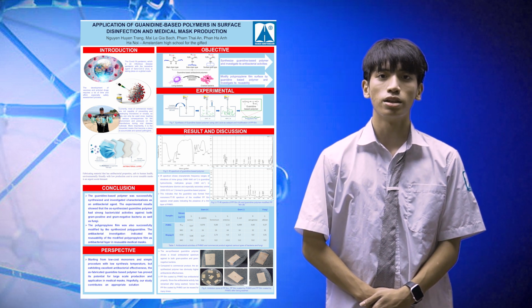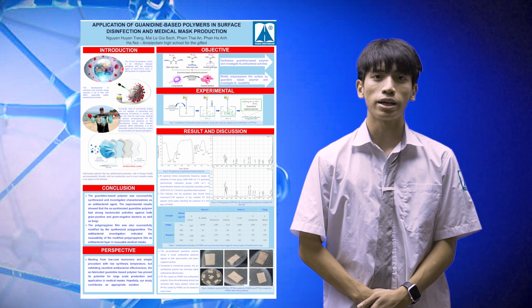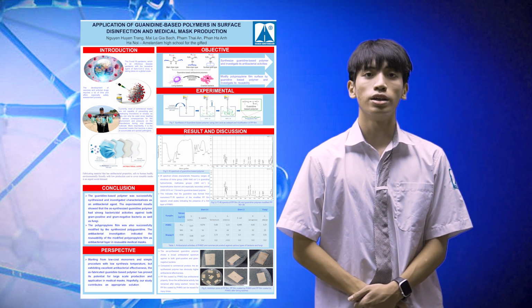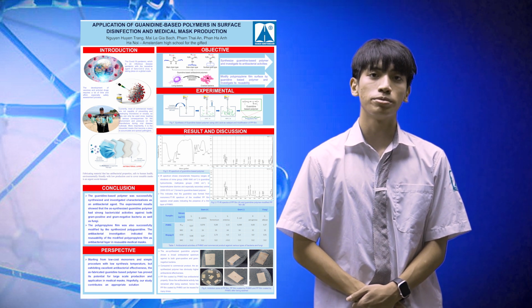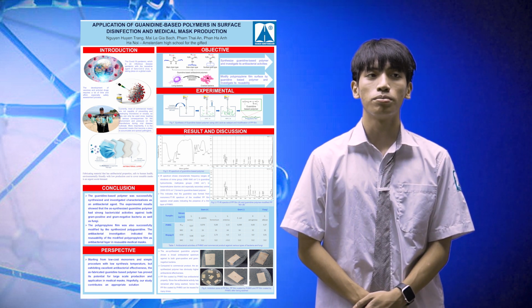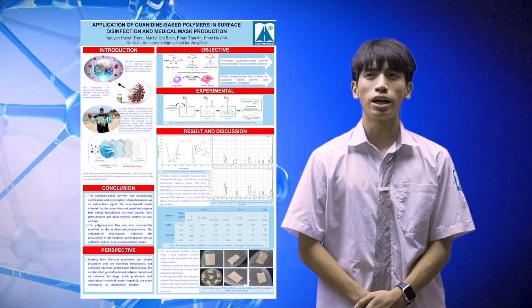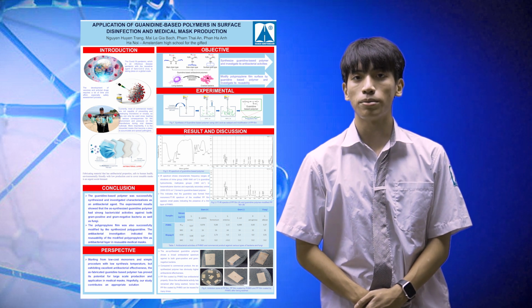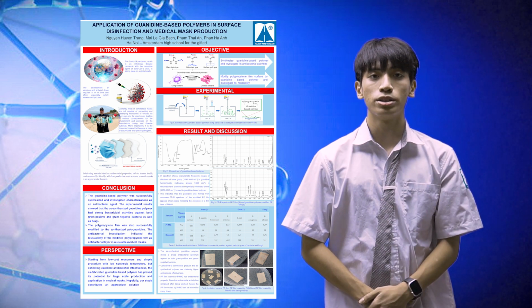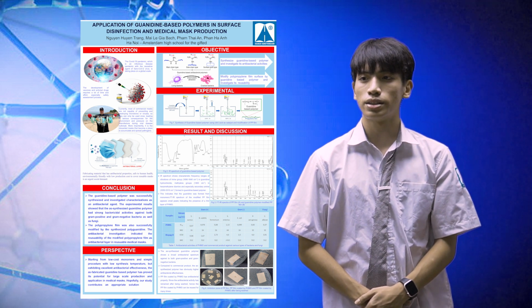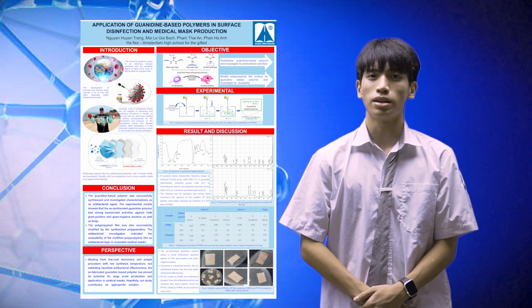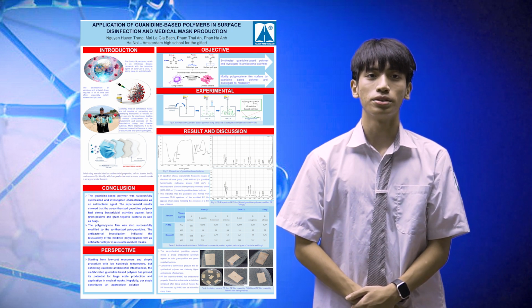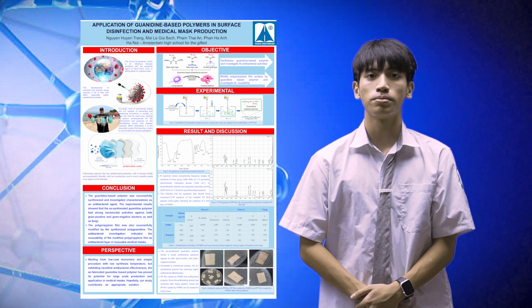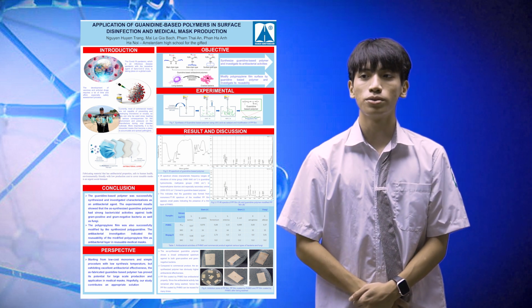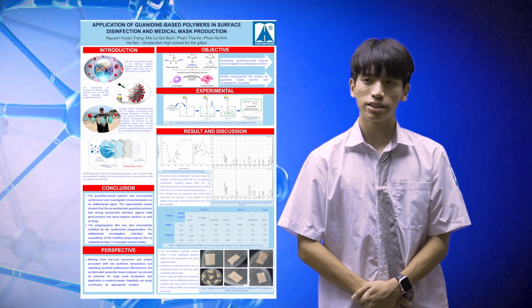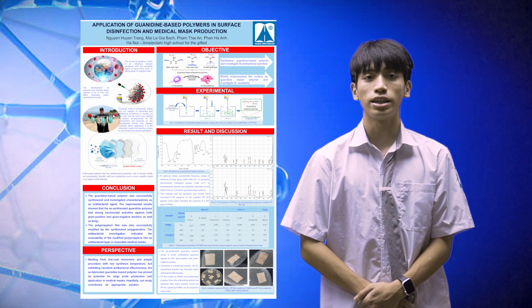To evaluate the application of PHMG in the production of reusable masks, we tested the inhibition zone of 3 samples against E. coli bacteria, including PP film coated by PHMG after being washed. As we can see, there is no inhibition zone around the PP film, implying PP itself has no antibacterial effect. Meanwhile, both modified PP samples, after and before being washed, show an inhibition zone with a relatively equal radius. It means that PP film coated by PHMG has antibacterial property. Since the antibacterial activities have remained after being washed, the PP film coated by PHMG can be reused many times.